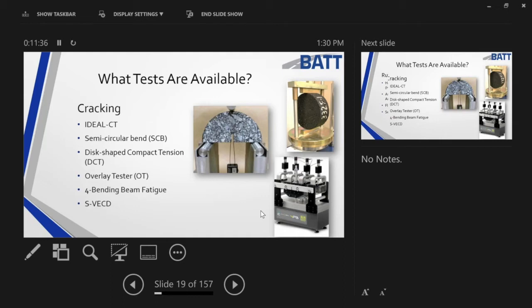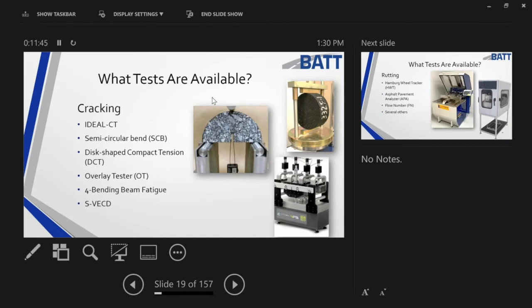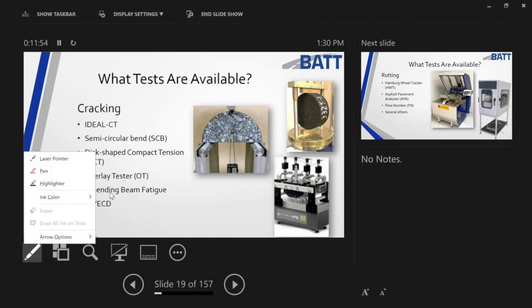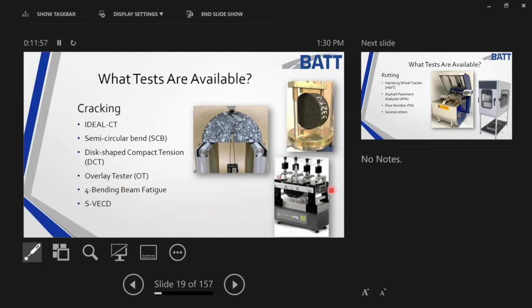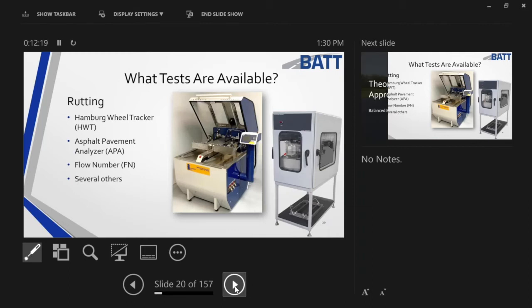These are just different tests that we can use, from the IDEAL-CT, which you see in the top right, which is also the same jig we would use for any IDT type of test or TSR test. The middle picture there is the SCB test. Of course, not pictured is the DCT, and we are also not picturing the overlay test, but we are picturing the bending beam fatigue test. Now, one thing you can look at is an S-VECD. That's a lot of letters, but it's a higher level test, and a very good test where I can actually glue the ends of my sample and measure in a pulling, or tension, mechanism the fatigue of a sample using an AMPT device.